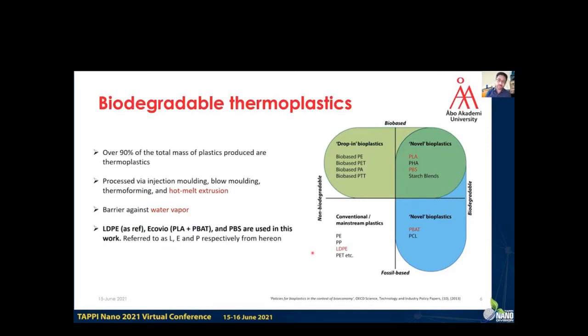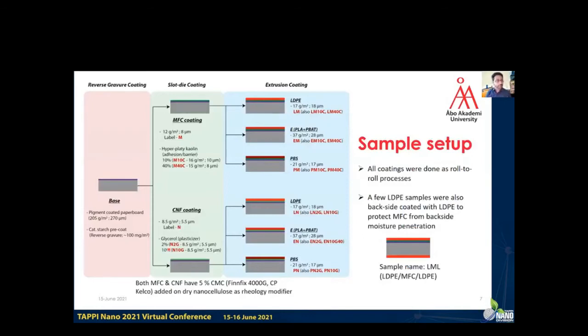So in this work, we chose representative plastics from each section. We used LDPE as a reference from the mainstream plastics, and then we used Ecovio, which is a commercial product blend of PLA and PBAT, and it has compostability certificates. And PBS is also a novel bioplastic, which is also in the green zone here and was also used in this work. All three polymers are labeled as L, E, and P respectively from here on. So if we look at the sample setup, we have a baseboard, which is pigment-coated paperboard, about 200 GSM grammage.